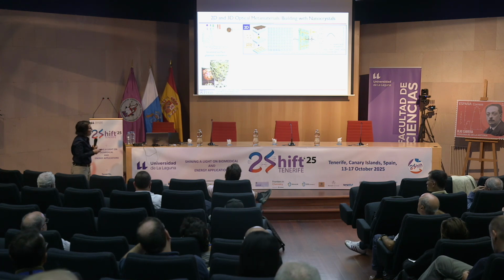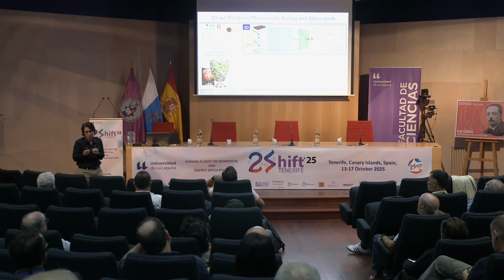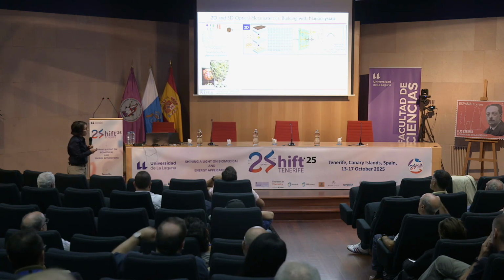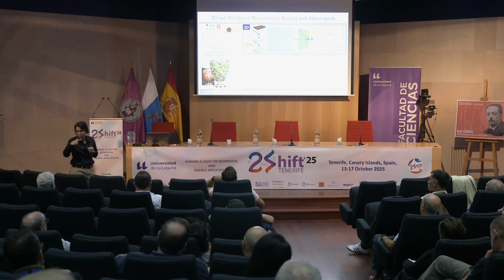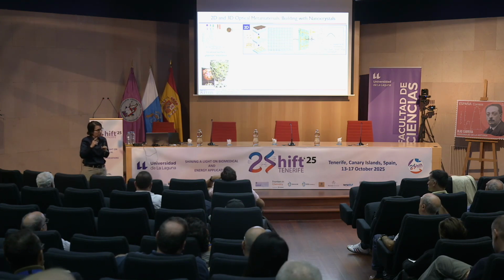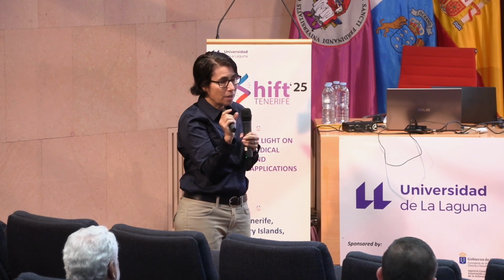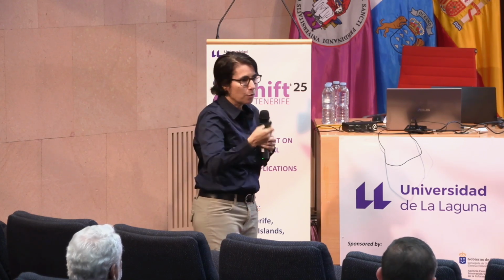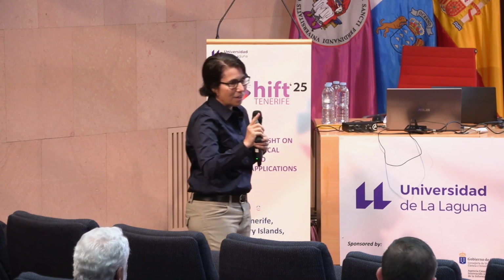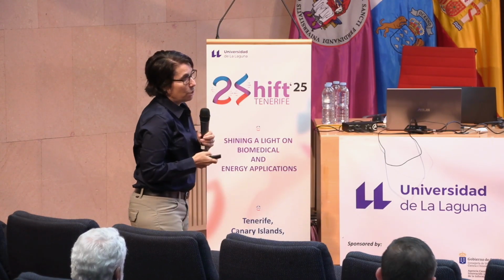We were interested in tuning dielectric functions, and here is an example where we showed that you could take these processes and build quarter wave plates. With our colleague Andrea Liu, he designed this structure where the rods in the vertical and horizontal direction are slightly different in dimension, which means their resonances are slightly detuned spectrally. So you get a resonance for one and a resonance for the other, in X and Y, and in between those two resonances you get a 90-degree phase shift. That is the requisite for getting Ex and Ey off by 90 degrees, and it lets you make a quarter wave plate.